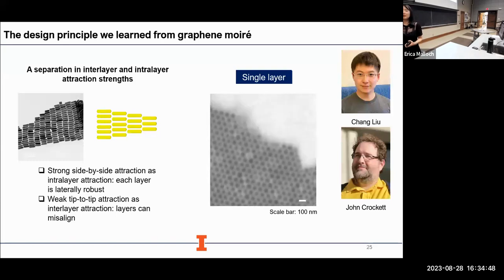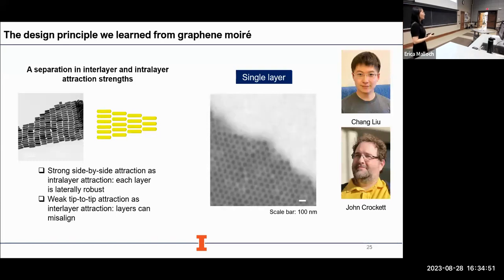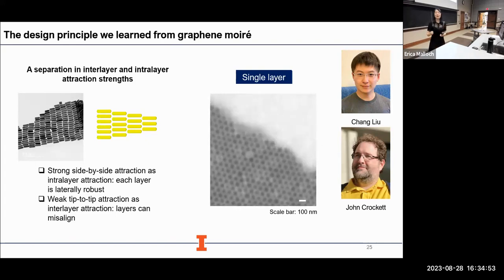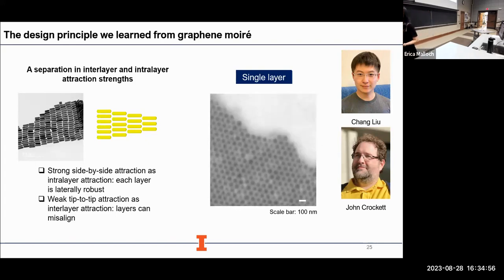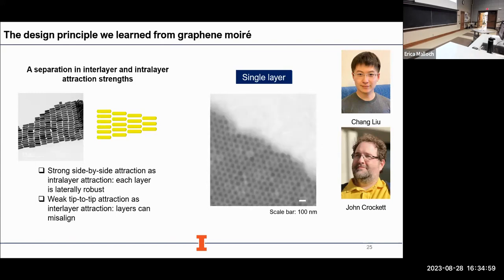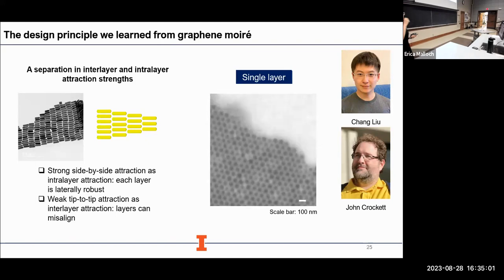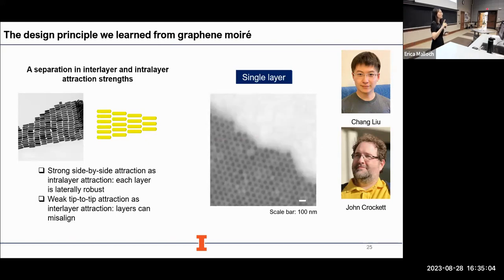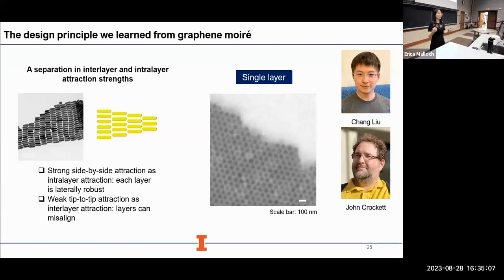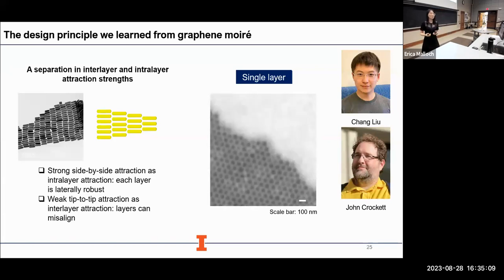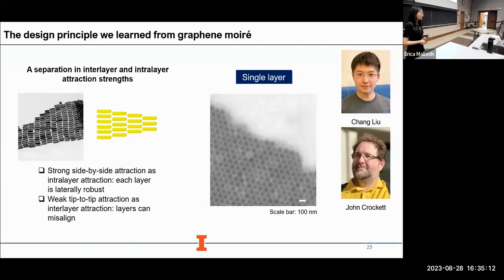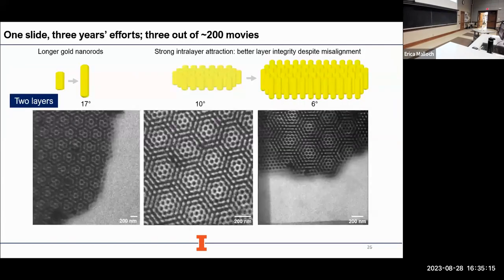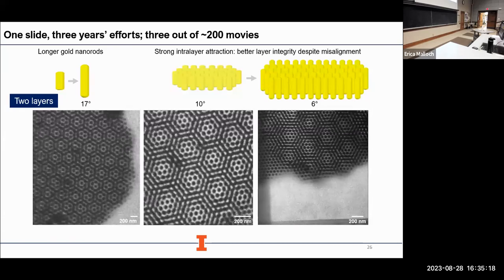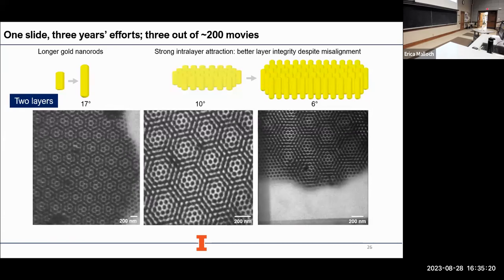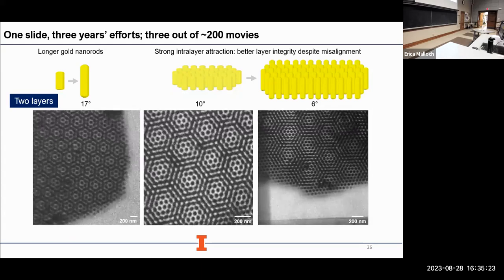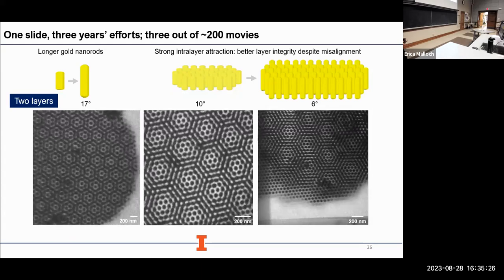So that's actually one unique feature using a nanoparticle building block in comparison to atomic building block. In graphene arrays, the interatomic potential between carbon atoms are basically fixed. But when it comes to nanoparticles, you can actually change the length, change the width, or change the aspect ratio of those nanorods. You can have a huge tunability space in terms of interparticle, intraparticle interactions. And then Chang further have the magic to actually have two layers of hexagonal lattice standing upon each other. And here you are seeing really a diversity of moire patterns self-assembled from gold nanoparticles.